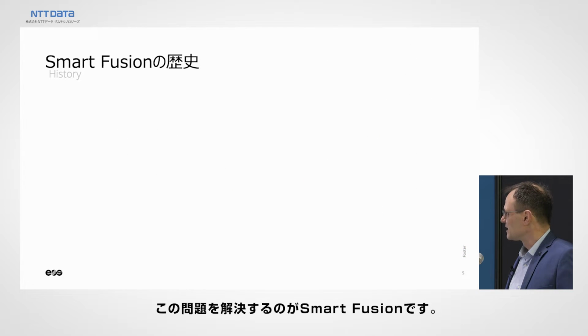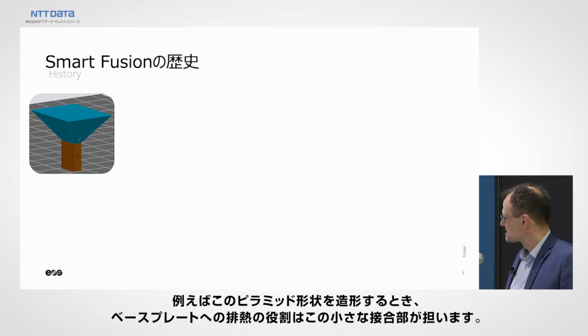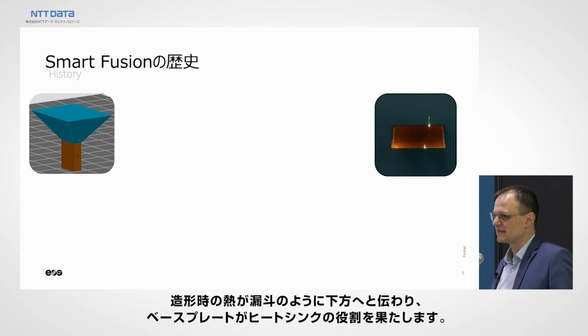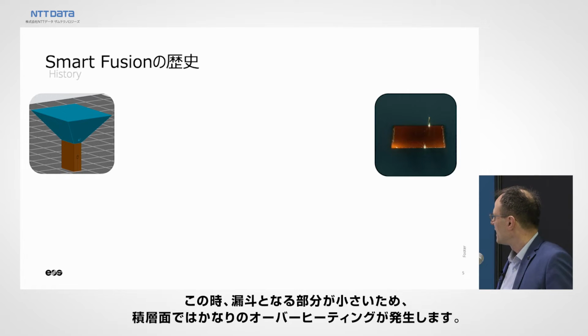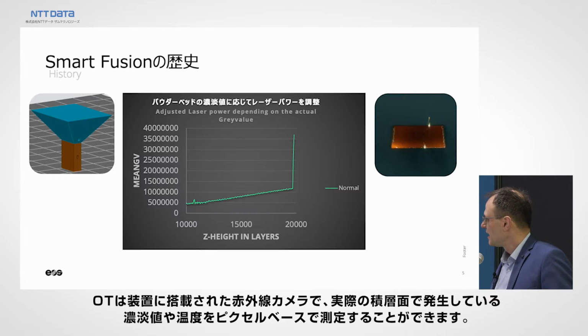Now going back a little, telling you what Smart Fusion really is and what it does. For instance, take this geometry. If you want to print this pyramid stump on a little connection down to the base plate, the heat from the melting agglomerates and has to travel down that little funnel into the base plate, which acts as your heat sink. And this is something that you don't want to see in the process, because that means you have a massive overheating of your actual layer.